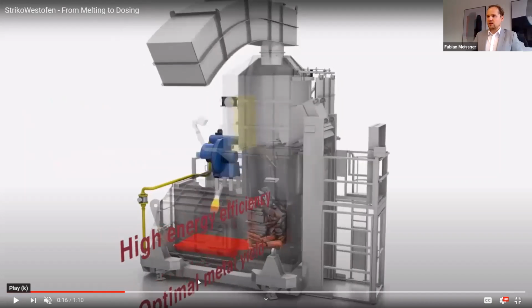And yeah, you can find the perfect moment for charging the new material into the shaft with a shaft laser. You can see it here. It's a laser that is going into the shaft and scanning the filling level of the shaft, and when it's below a certain point, then it will start charging again. This makes sure that we have a perfect filling level that achieves the lowest energy consumption in the shaft. Then you can see here the yellow part, that's a baffle or flue cover. This cover is closed once the furnace is charged to make sure that the heat is kept in the furnace.